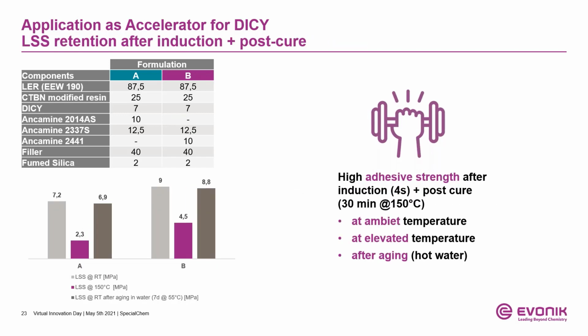To check the lab shear strength retention capabilities under different influences, induction pre-cured samples as shown before were post-cured for additionally 30 minutes at 150 centigrade. And the lab shear strength was evaluated at room temperature for reference and compared to samples which have been aged in hot water for 7 days prior to the measurement.